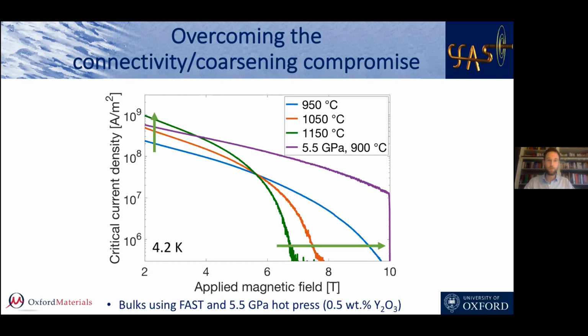So we did overcome what we thought was impossible, that compromise between improving connectivity, which requires high temperature, and also decreasing coarsening, which actually prohibits the use of high temperature. So using a new sintering process is actually quite interesting to overcome limitations of simpler processes which only use a low amount of pressure.